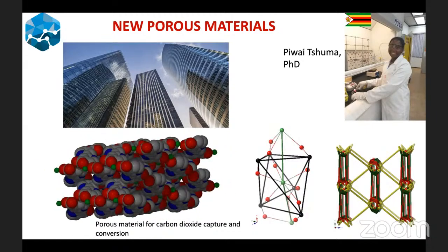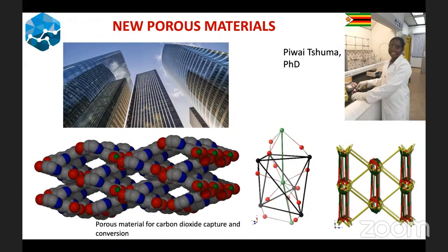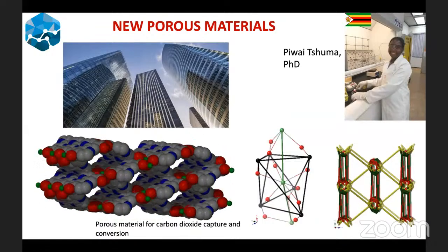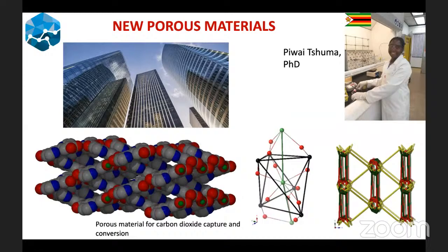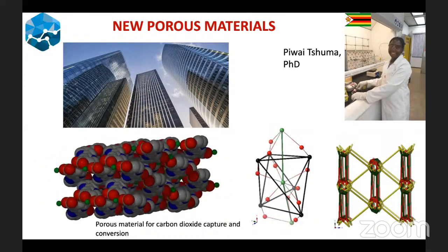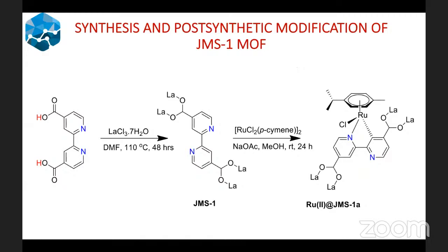The whole idea is to insert highly active complexes of ruthenium or palladium, and then we carry out catalysis under heterogeneous conditions. So one of the ligands that we chose was this compound. As you can see, it has some nitrogen functionalities. And then we took this ligand, and under appropriate conditions with lanthanum chloride, we managed to isolate a MOF.